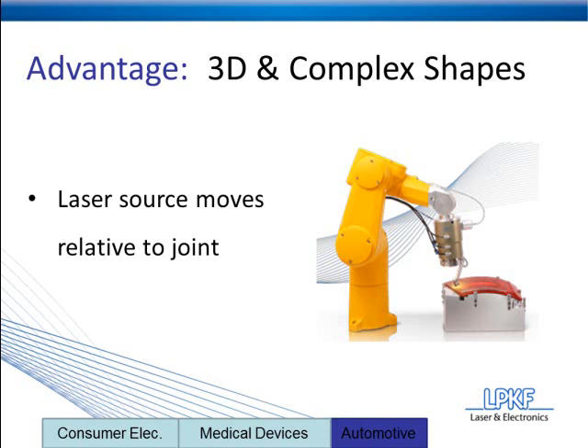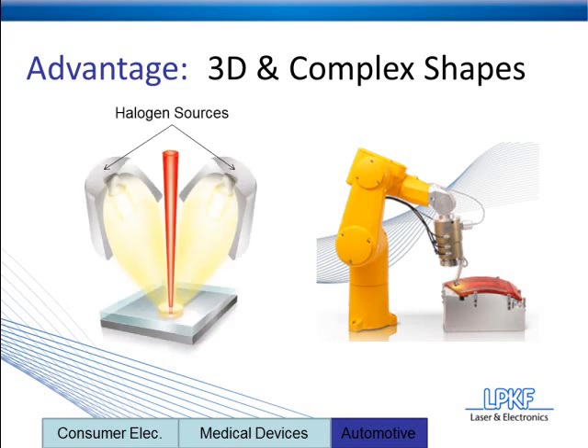There's also one more thing I wanted to mention about the TwinWeld 3D system, and this does fit quite well with 3D and complex shapes, and that's a proprietary technology that uses halogen heat radiation in addition to the laser radiation. So there's really two clear advantages to this, the first being that the halogen heat sources will soften and anneal the plastic. Now, when you're dealing with 3D and complex shapes, it's going to be tougher to get a really nice fit between the two parts. If the plastic is softer, though, it's going to tend to fit better together.